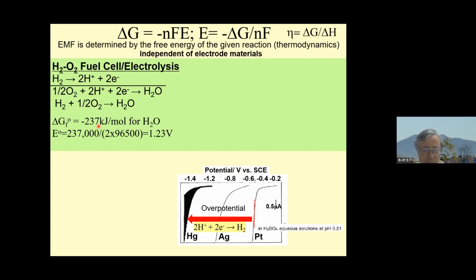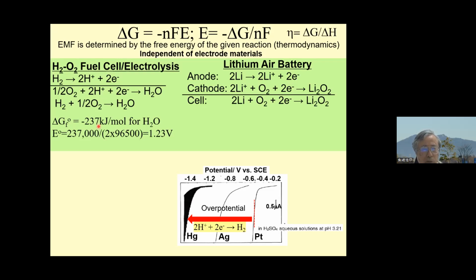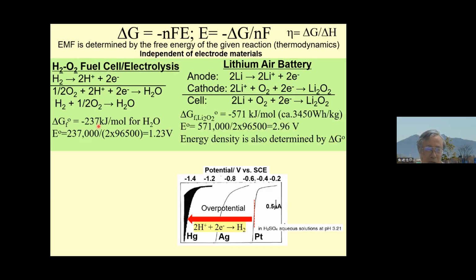However, if you look at the real situation, this is the hydrogen evolution in acidic solution at platinum, silver, and mercury. In the case of platinum, the hydrogen evolution started at the theoretical potential, but silver required more potential to be applied, and mercury requires more than 1 volt more than platinum. So also in the case of the battery, this is a lithium-air battery which we are studying now. In this case, from the free energy of formation of lithium oxide, we can calculate the potential, or voltage, as 2.96 volt. And we can even calculate the energy density from this free energy, because free energy is in kilojoules per mole, and you can convert it to watt-hours per kilogram. So this 3,450 watt-hour per kilogram is really high.